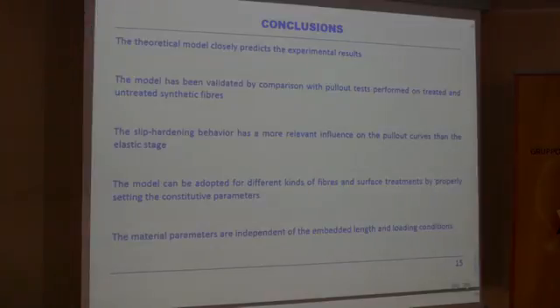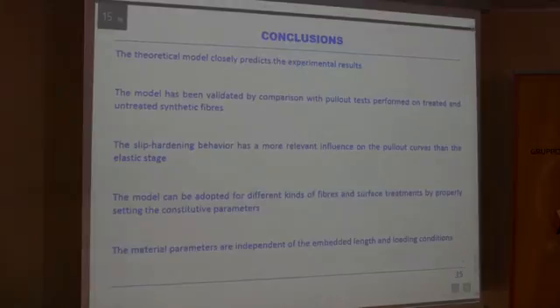In conclusion, we see that the model accurately predicts the experimental results, both for treated and untreated fibers, and the slip hardening behavior, actually the last part of the pull-out curves, has a more relevant influence on the behavior of the pullout than the initial elastic stage. Actually, in a simplified model, the initial elastic stage can be neglected with respect to the pullout stage.